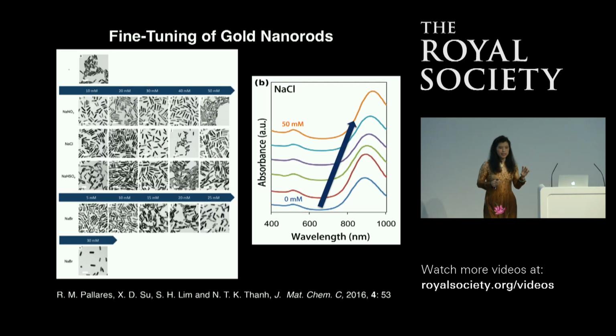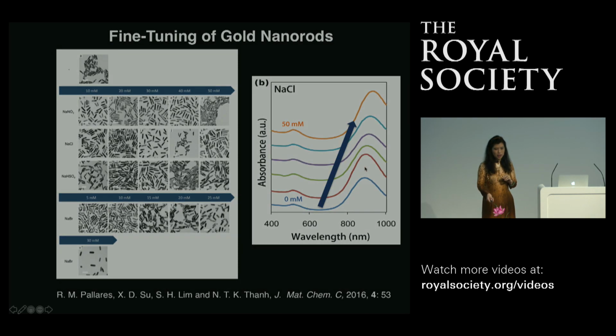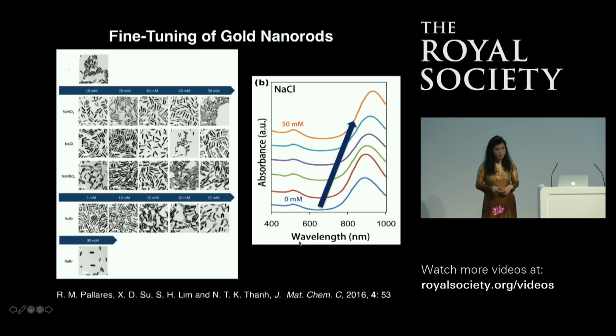So now what we do is make not even spheres. Well, the spherical shape is maybe a little bit boring, so we can go into the rod shape. And we can make them beautifully with a very fine-tuned aspect ratio. With the fine-tuned aspect ratio, you can tune the absorption to a longer wavelength. You can see that the original spherical peak is still there at 520, but it gets dampened. Because with the rod, the electromagnetic radiation interacts horizontally and vertically differently. That's why you get two peaks. And depending on the aspect ratio, you can move the position of the peak.